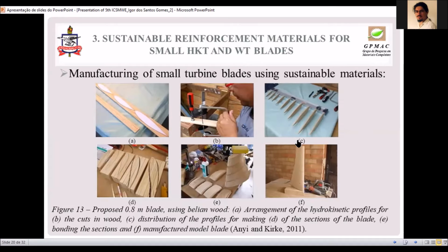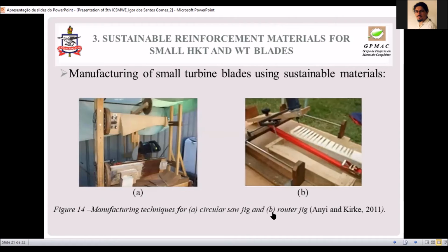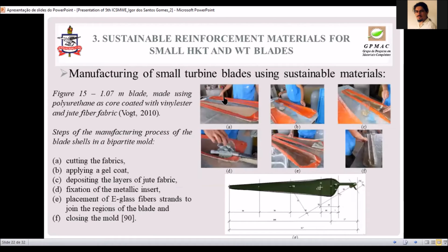In this case, for example, a blade is manufactured using templates for the profiles of the blades to manufacture the sections. They can be bonded together to manufacture a blade using a natural material, that is Belian wood. And from these blades, others can be manufactured by copying the blade, for example, using techniques with a circular saw or router. And there are manufacturing techniques that use molds to manufacture small blades. This technique was used to manufacture a 1.07 meter blade made using polyurethane as a core, coated with vinyl ester and jute fiber fabric, a fiber cultivated in the Amazonia region.